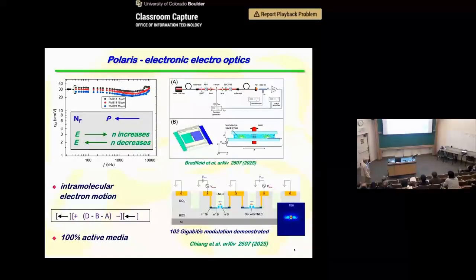the typical application is on a silicon optical chip where you make a channel, which is a waveguide. You have infrared light going down the waveguide. You have ferroelectric nematic with the polarization transverse to the propagation direction, and then electrodes you can apply a field. Now the advantage of small molecules is that we're not reorienting the molecules here, we're sloshing electrons back and forth in the chromophoric molecules. And in molecules, this is an extremely fast effect. And they've demonstrated this at 102 gigabits per second so far, hoping to get to the terahertz regime.